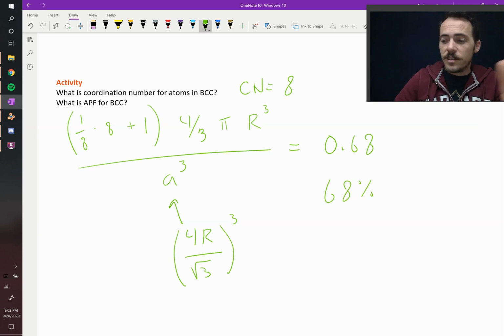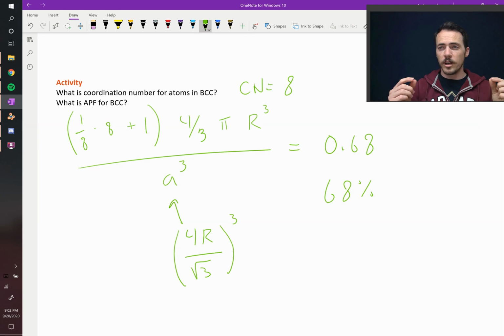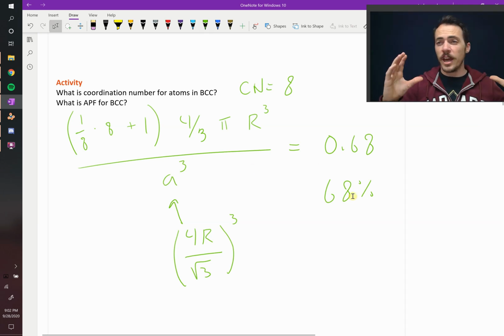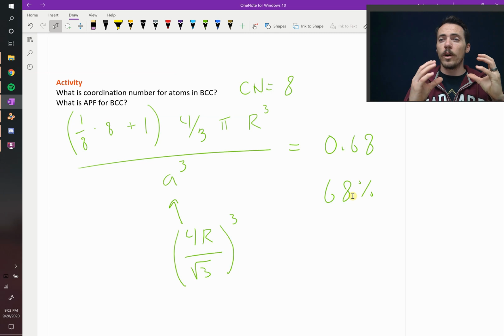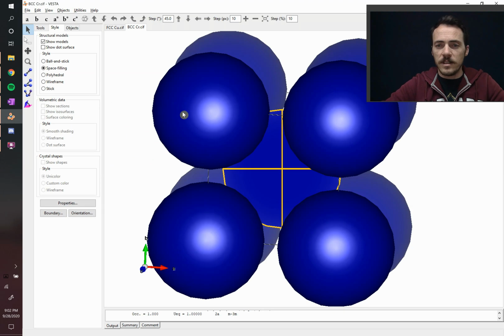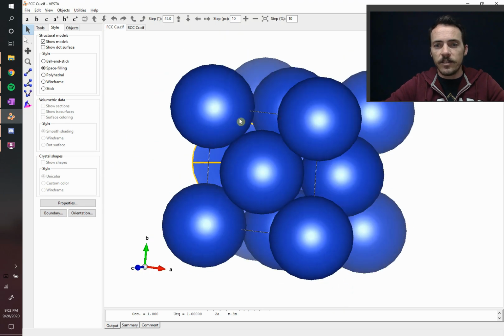In other words, it doesn't pack as closely, but we knew that because from the steel phase diagram, we knew that the room temperature alloy was BCC, and that when we heated it up, it turned into FCC, and it shrunk. Well, that's because you went from 68% packing to 74% packing. It had to squeeze those atoms closer together, and so the wire shrunk. Since you weren't creating new atoms, it just squeezed together a little bit better. So that's the difference between BCC and FCC lattices.